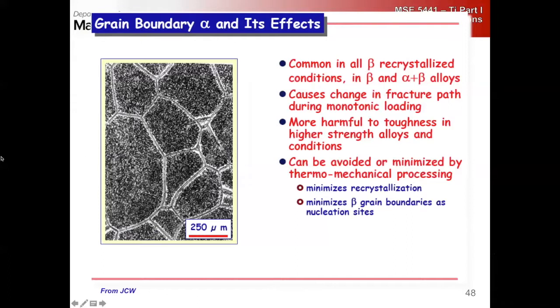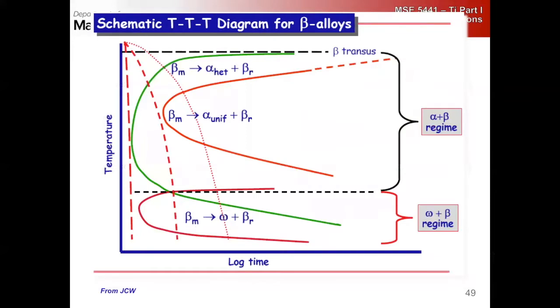And the thing about this is it's quite detrimental to toughness, because this grain boundary alpha now becomes a short circuit fracture path. We have long straight regions. The crack doesn't have to take a tortuous path through this composite microstructure through the middle of the grain. And so again, we want to retard recrystallization and minimize the number of beta grain boundaries as nucleation sites, which again means we need to put enough work in there to get a nice distribution of omega or beta prime or martensitic phases that can then act as nucleation sites.